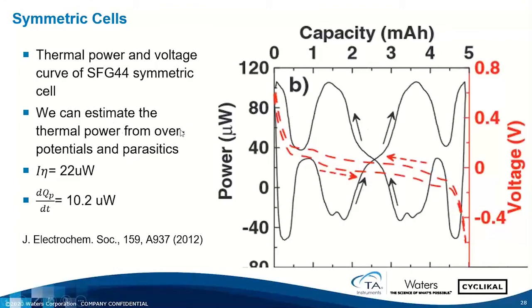From a plot like this, we can estimate the thermal power from overpotentials and parasitics. At this midpoint here, the two electrodes are exactly the same state of charge. And if there were no thermal parasitics, it would be zero heat flow, but there are some. And those come from the polarization, which can be arrived at by the overpotential associated with this hysteresis between the charge and discharge, and the remainder being due to the thermal parasitics. So we're here at this cross point of just over 30 microwatts, and you can see it's well accounted for by those offsets. And the full story of this can be seen in this piece of work.